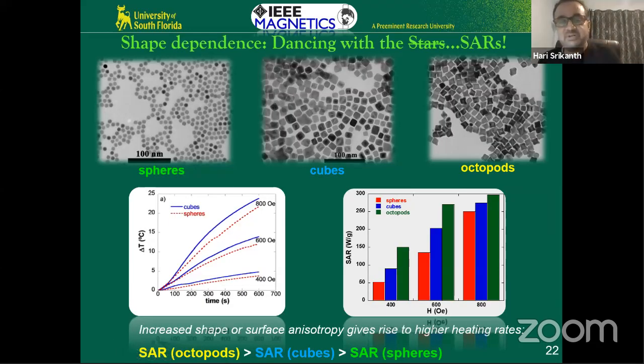And this is perhaps the most important slide of this presentation. We were one of the first groups to show that as you increase the anisotropy, as you go from spheres to a lower symmetry system like cubes and a higher anisotropy system like octopods, you see that the SAR goes up for the same biocompatible system. We don't need to go to different materials. We don't need to go to different oxides. For the same system, we can increase the SAR by playing around with the shapes, and in this case, the surfaces. So this is the message that I wanted to give you, that even with a basic, well-known system like magnetite, Fe3O4 iron oxide, you can still do a lot of interesting things by doing surface modification, by doing careful chemistry, and making sure that you're able to controllably change these particles.